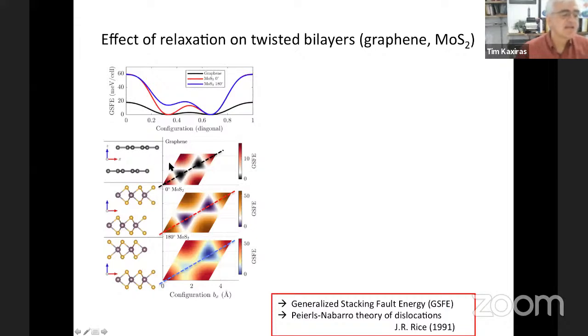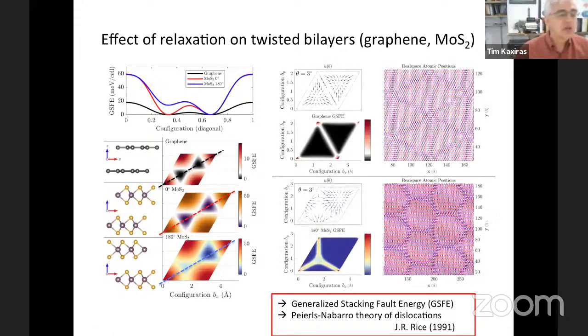So now you can take this energy landscape, which is just energy as a function of sliding, and use a very nice theory that was introduced about 30 years ago by Jim Rice, based on the theory of dislocations, and use this to produce the atomic configuration. So this is essentially the gradient of this energy landscape. You take this energy landscape, you calculate its gradients, and the gradients can give you the atomic relaxation. So this is what I'm showing you here.